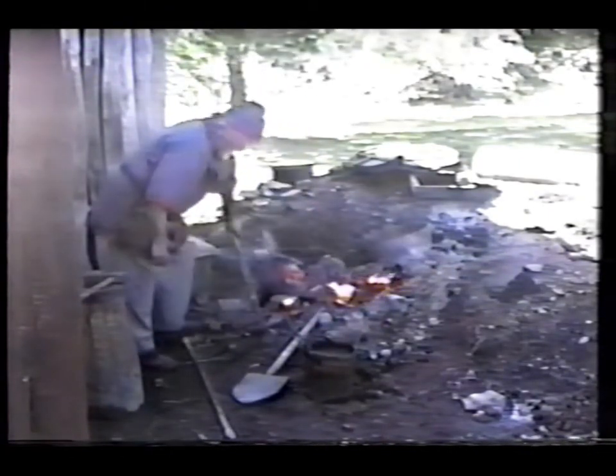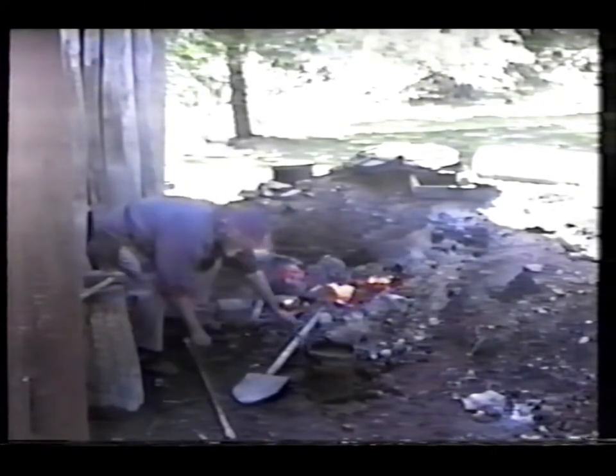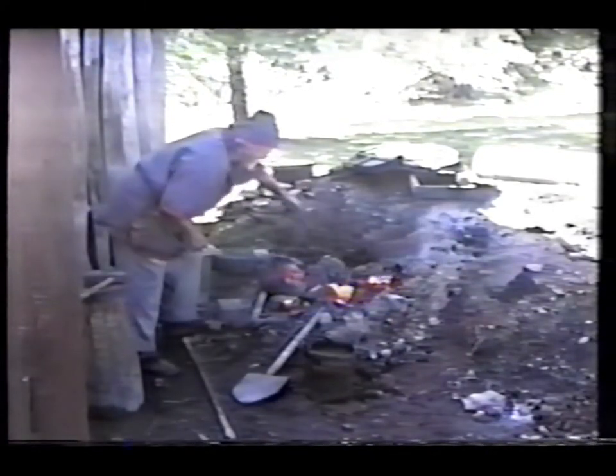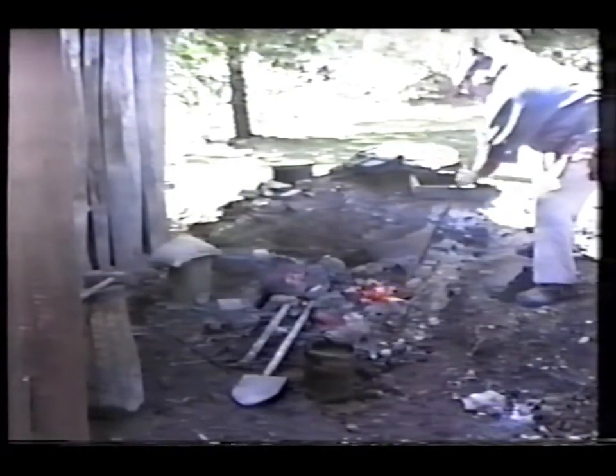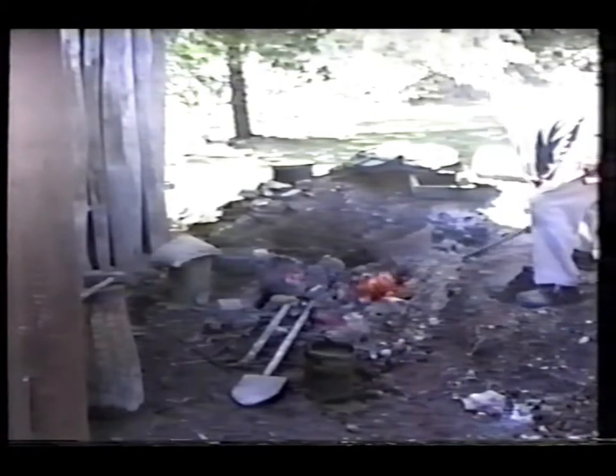This bloom would be fairly typical of most dark age ones, weighing in at around 20 or so kilograms, which is, no sorry, 5 kilograms. Us oldies don't handle the metrics too well. About 10 pounds of iron, a few pounds of slag, so about 5 or 6 kilograms of iron would have resulted, which is typical of excavated.